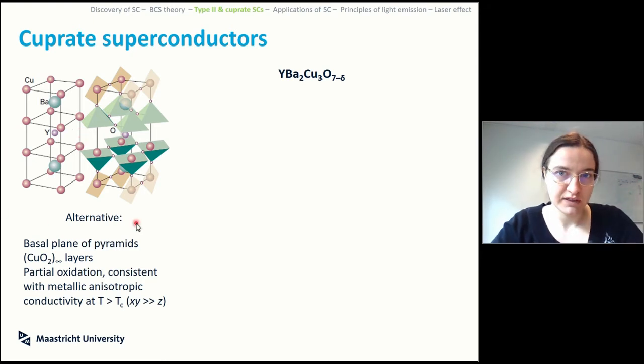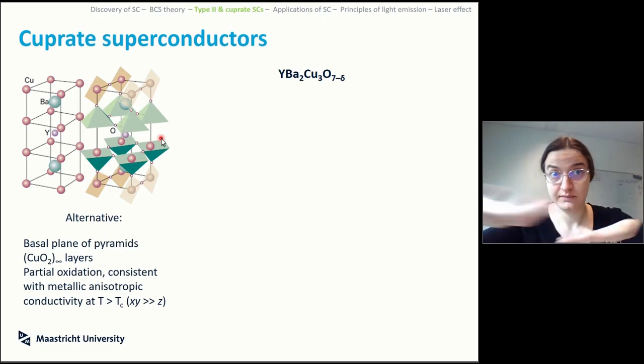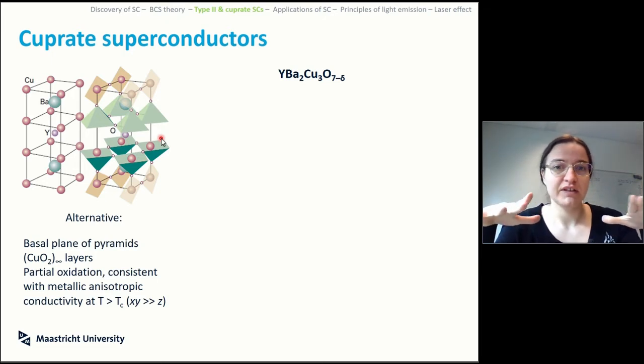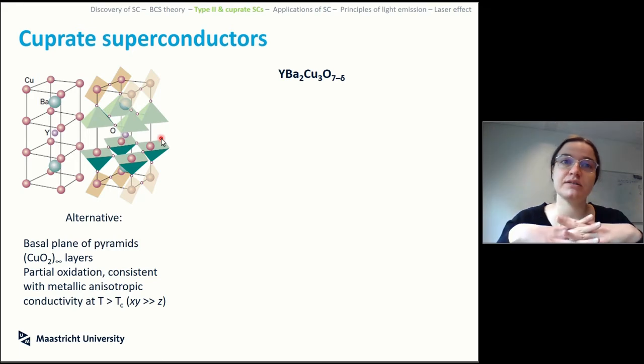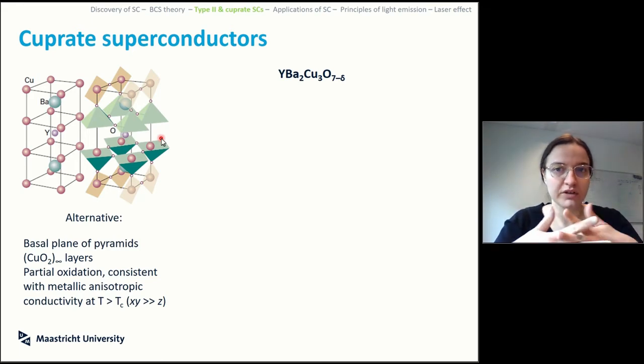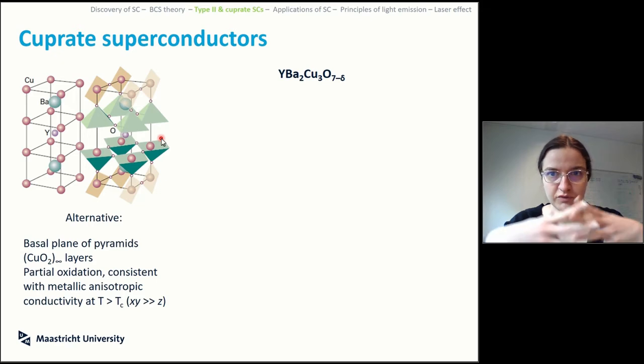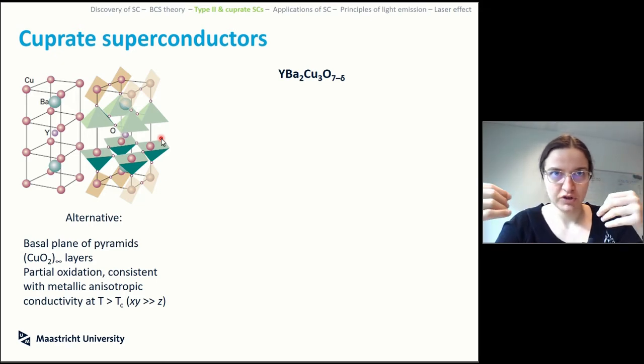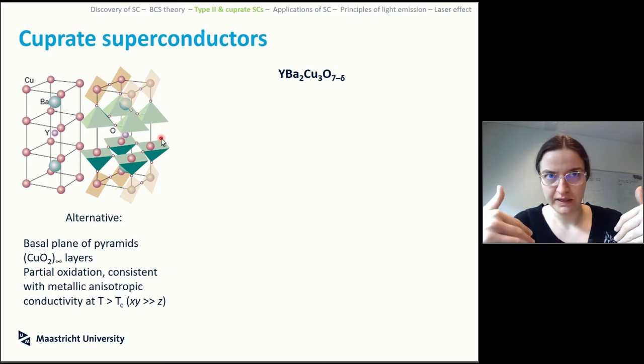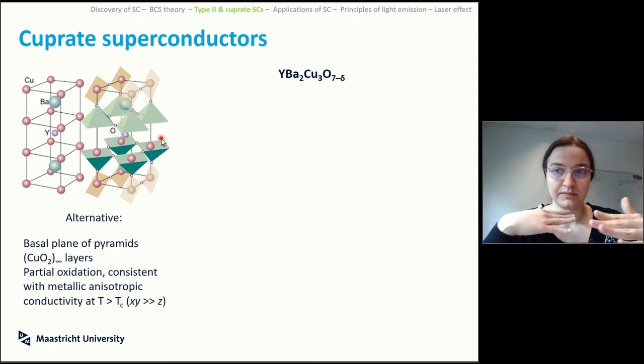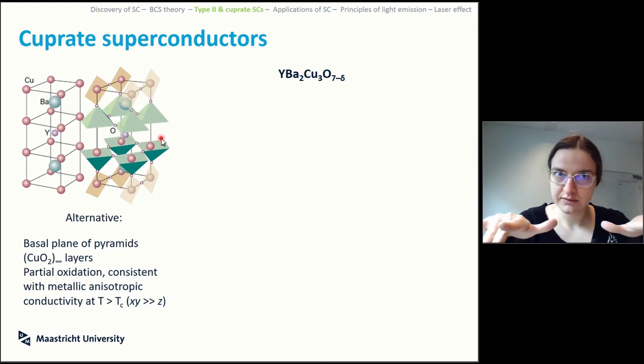But the alternative view of this thing is that basically you regard the base of the pyramid as a CuO2 infinite sheets type of stoichiometry, and you have this partial oxidized. But now this kind of begs the question of what is going on in the bands, because you will have the copper and the oxygen with their 3d and 2p orbitals. If they overlap with this partial oxidation, you will have a metallic state, right? And this is actually something that you see, so we can prove it, because you have a metallic normal state.